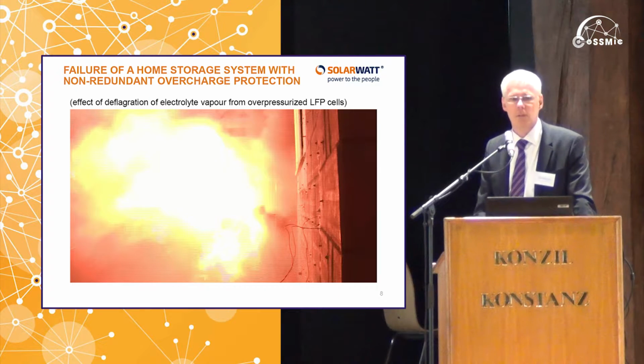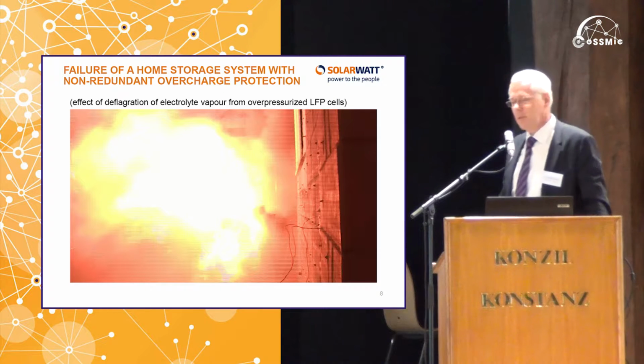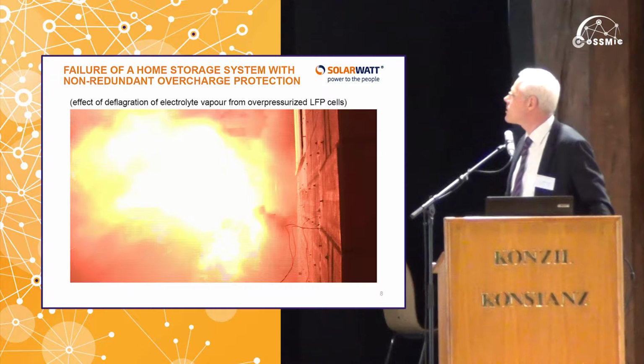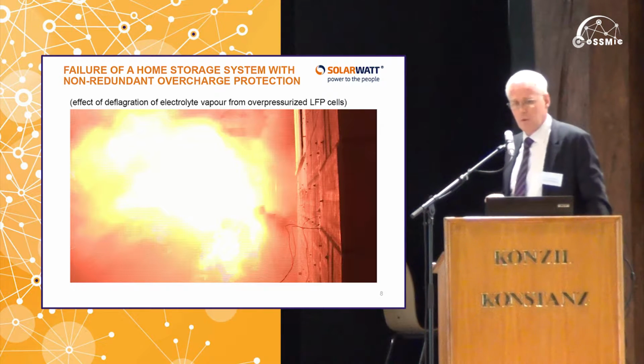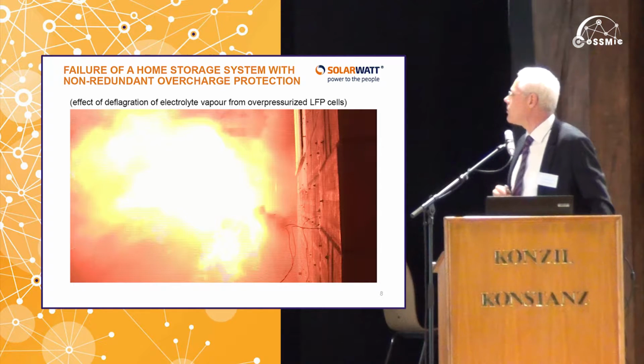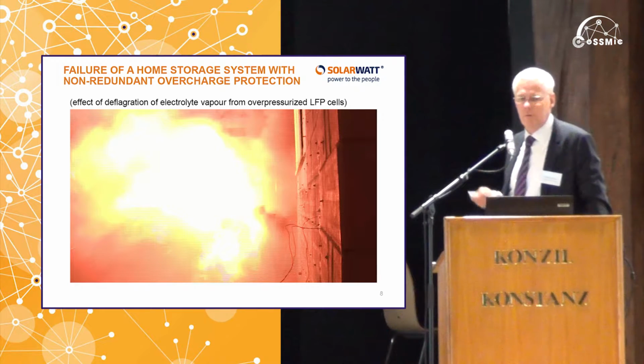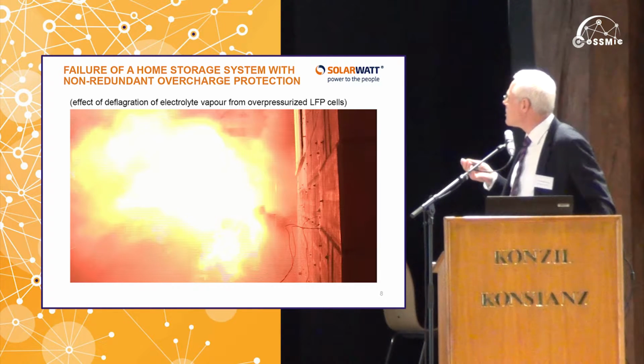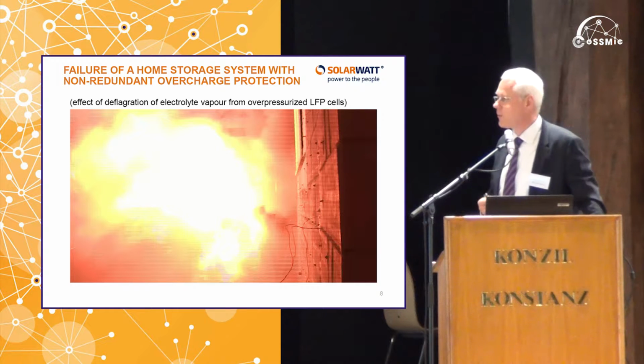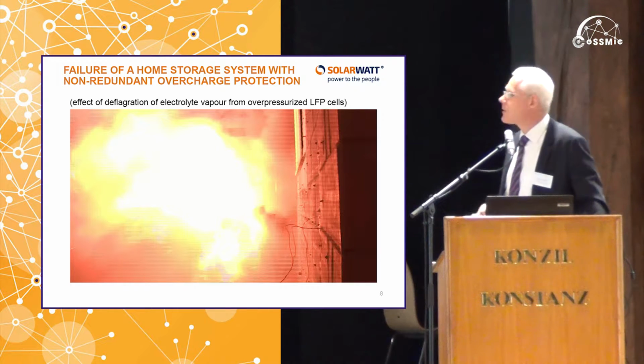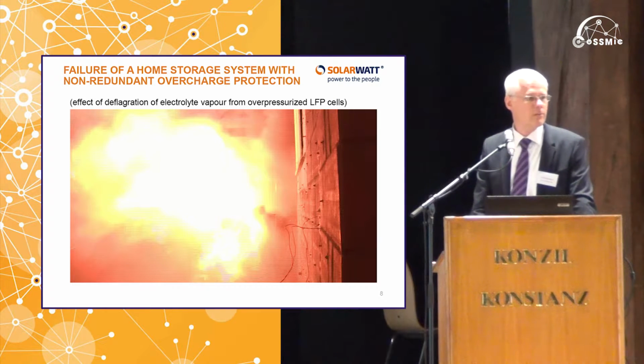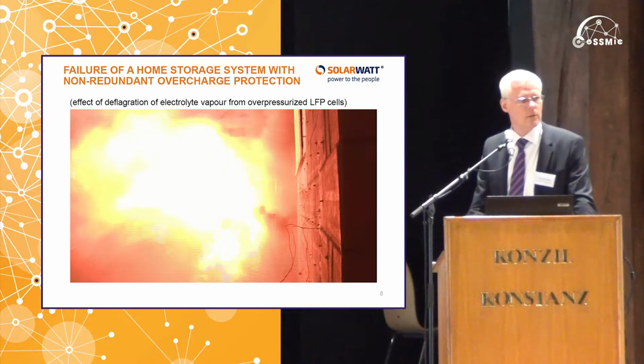And what happens if such a system fails to prevent, for example, the cells from overcharging? You can see here, this is a failure of a home storage system. This was a commercial system with a non-redundant overcharge protection. And you can see here the deflagration of the electrolyte vapor coming out of the cells. They have been overcharged due to a single fault in this home storage system. And by the way, these are lithium iron phosphate cells, these cells of which some manufacturers still claim they cannot burn, which is stupid, obviously, as you can see here. So this is really a dramatic event, and all of the, I would say, quality home storage manufacturers take a lot of effort to make sure that this never happens in their systems.